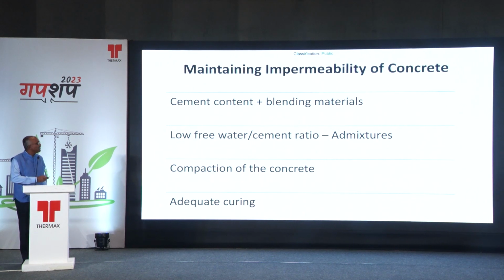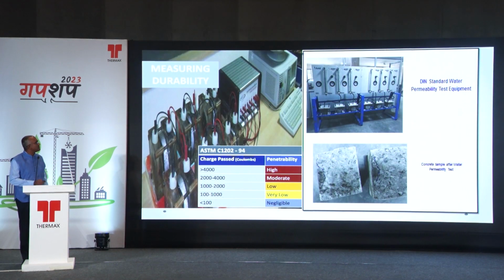All this, of course, ensures that the concrete is impermeable. Some of the durability tests, as Savantji had mentioned, but many times they are not being done. Like, for example, the RCPT test, a very simple test wherein the concrete specimen is kept, with sodium hydroxide on one side and sodium chloride on the other, you maintain a voltage using a DC supply, and then you try to find out how many coulombs are passing through that concrete specimen, and based on the quantity of coulombs, you determine if the concrete is durable or not.